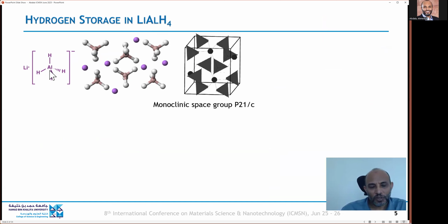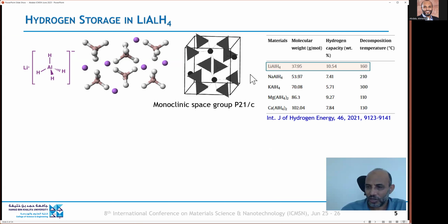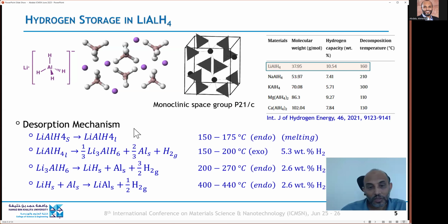So today we're going to focus on enhancing lithium aluminum hydride, which is basically an anion of aluminum coordinating with 4 hydrogen atoms, and then that anion complexes with a lithium cation, forming a monoclinic crystal structure with a hydrogen capacity of about 10.5% and a decomposition temperature of about 150 to 160 degrees. Among these, lithium aluminum hydride has the highest storage capacity and intermediate release temperature. So if we can reduce the hydrogen release temperature, this would be a significant material.